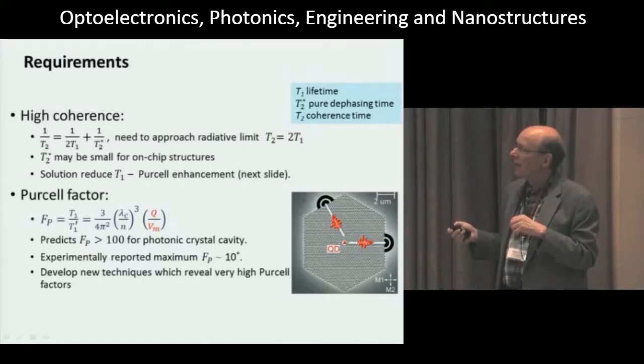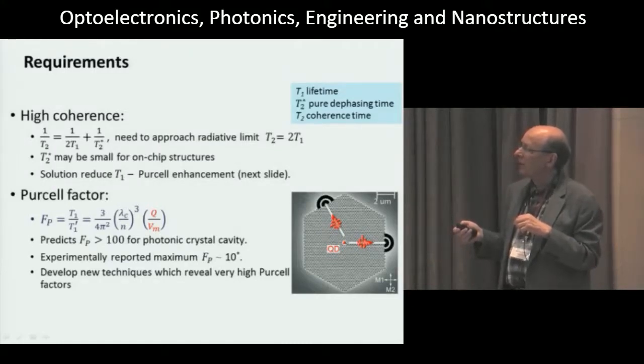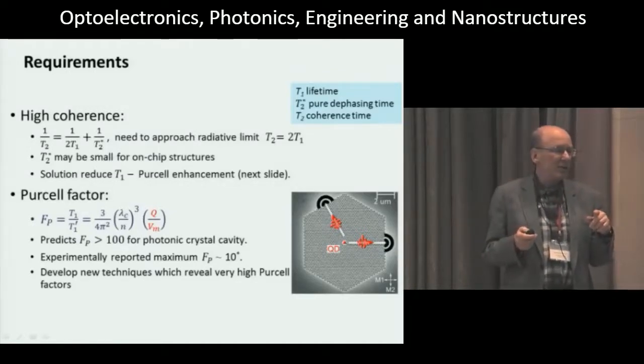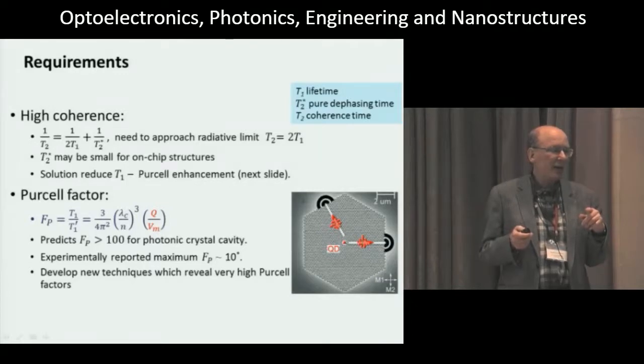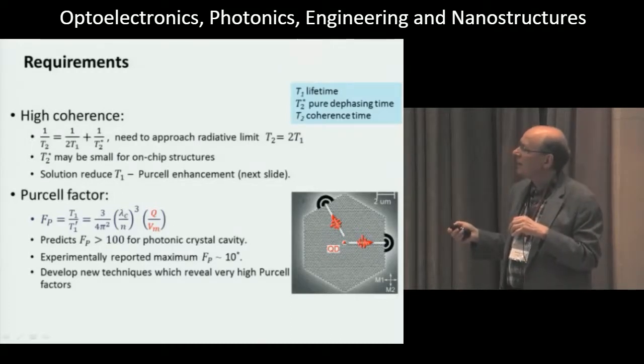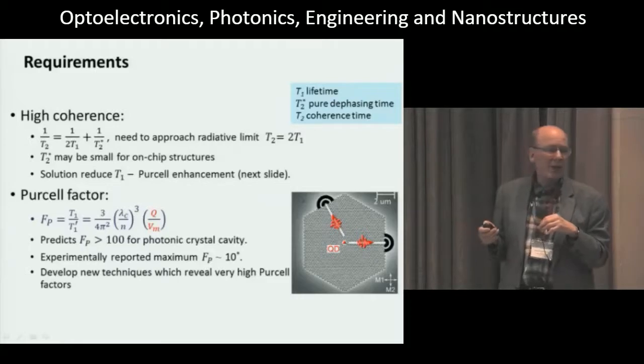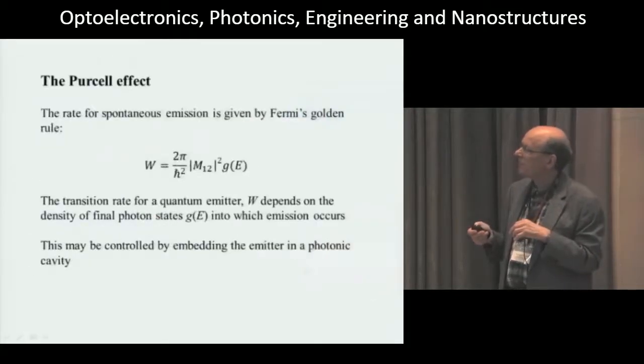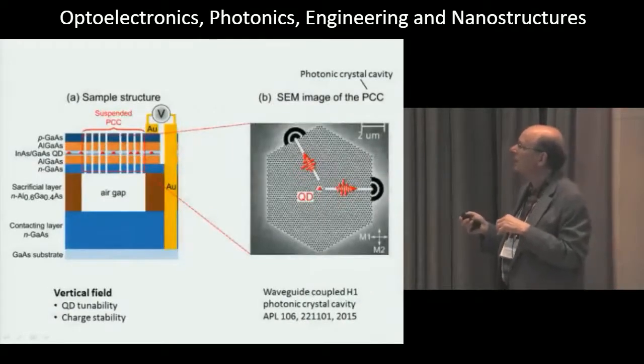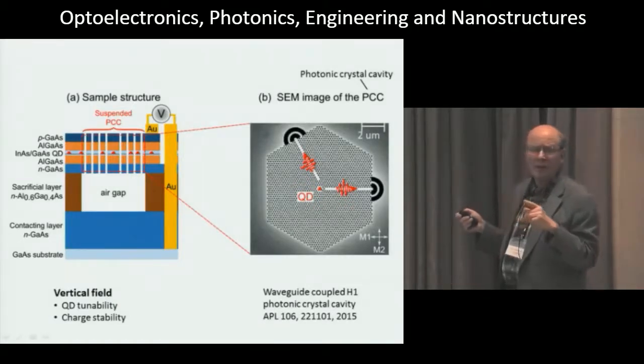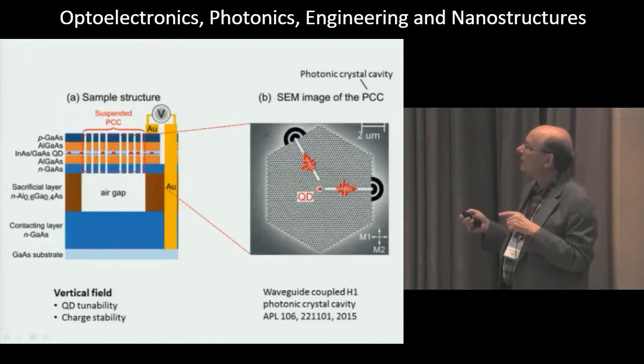And again, within the limited time available, I can't describe all the details, but by developing new measurement techniques, we're actually able to measure Purcell factors up to about 40. So it was not that the Purcell factors were limited to 10, it was the difficulty to actually measure very large Purcell factors. So this is the type of structure we're dealing with. So here is a photonic crystal with one missing hole. So this is the cavity. So the volume is very small. And because we're dealing on chip, the modes of the cavity are coupled to waveguides, and the photons are then detected externally.